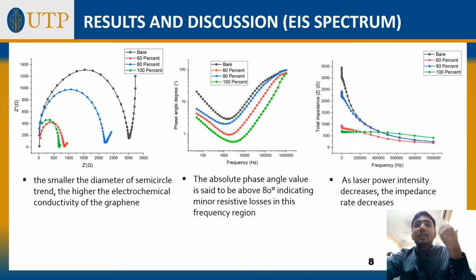The third one is the impedance against frequency graph, showing that as the frequency increases, the impedance decreases. As impedance decreases, it's also known as an effective resistance decreasing. So thus, as laser power reduces, the impedance reduces, making 60% graphene the best graphene sample due to the lowest resistance rate and highest conductivity rate, enabling good mobility rate.